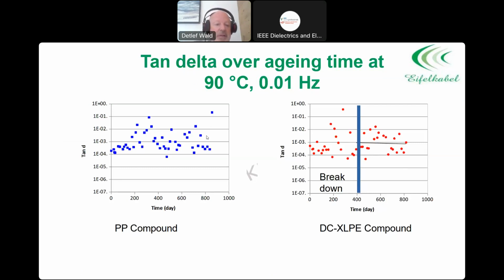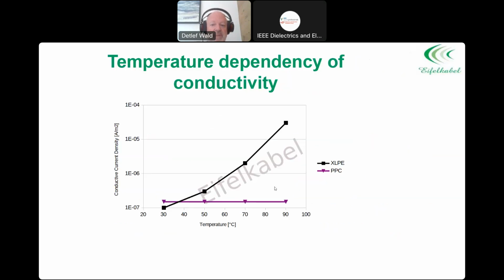About aging, here we measured the tangent delta over time. You can see a big spread, but over aging, the issue is you're creating carboxyl groups, which are polar, and that means you have an increase in tangent delta. The issue here was also that we had the first breakdowns with XLPE roughly after 1 year and some months in that test. There are new tests set up, and they hopefully will report it soon.